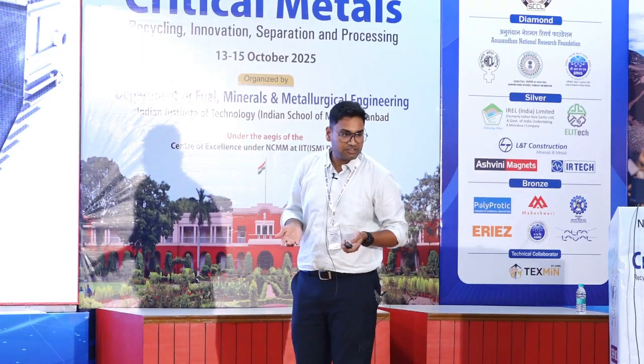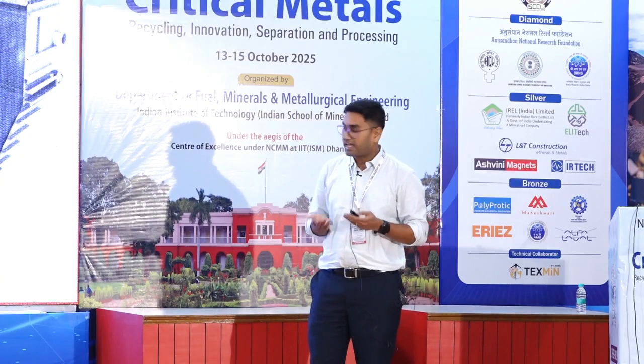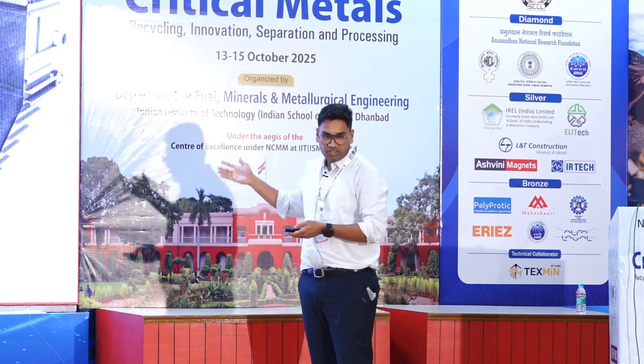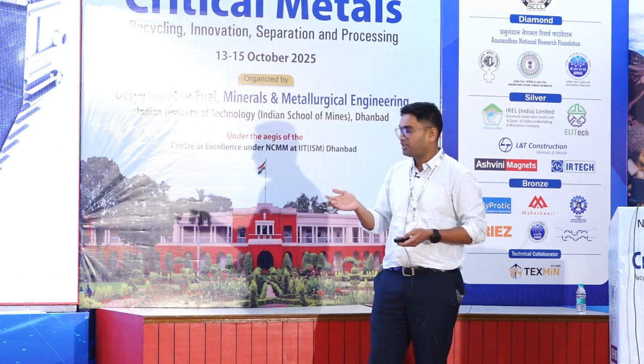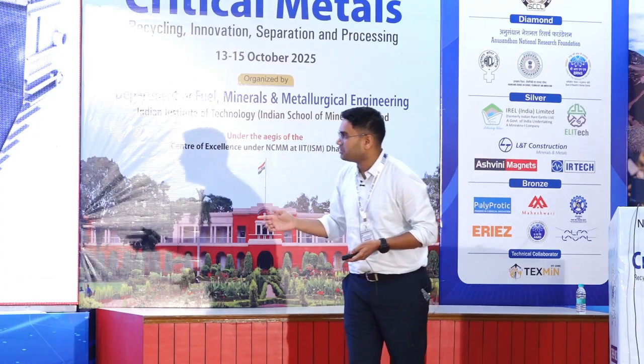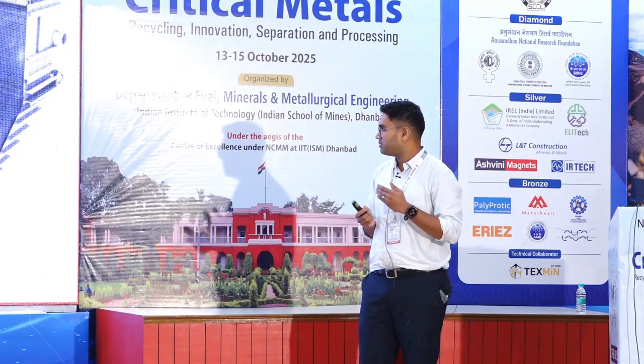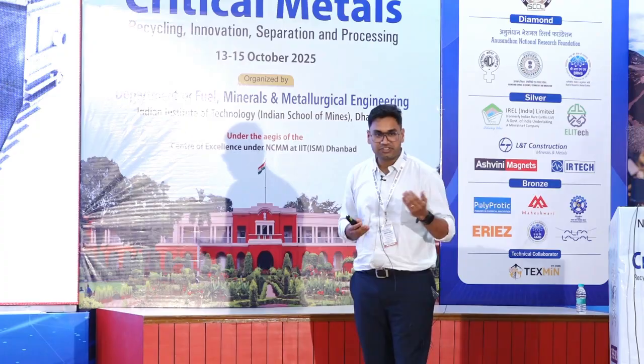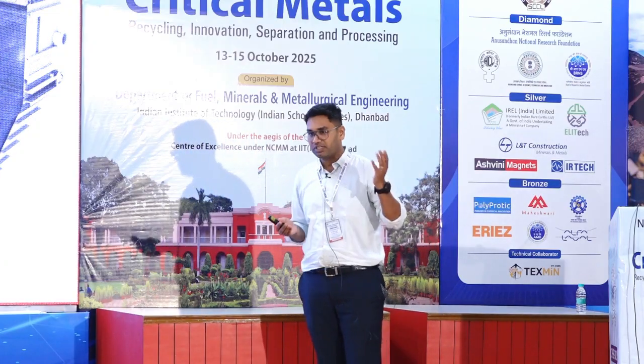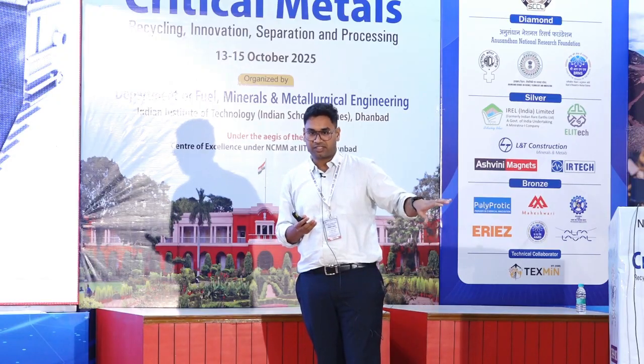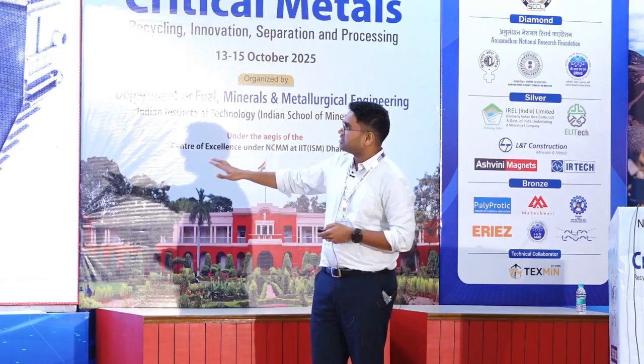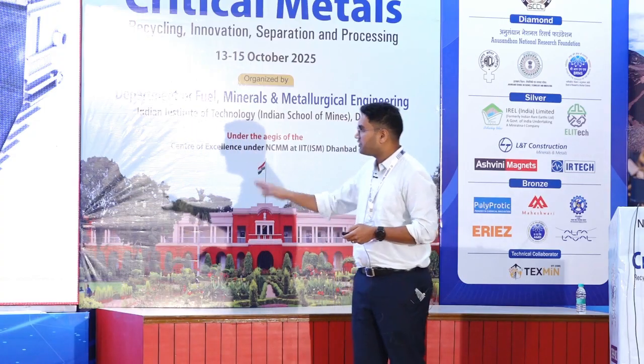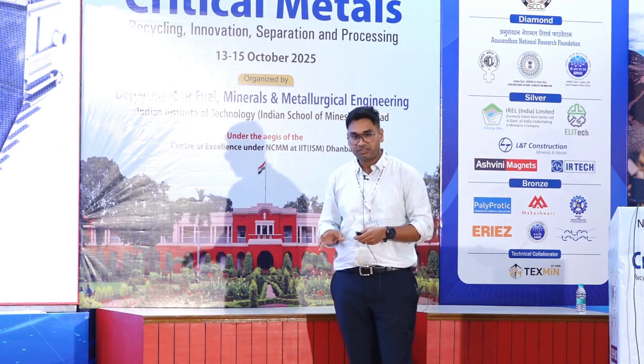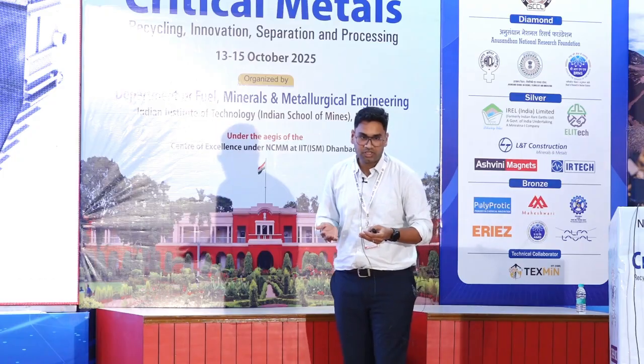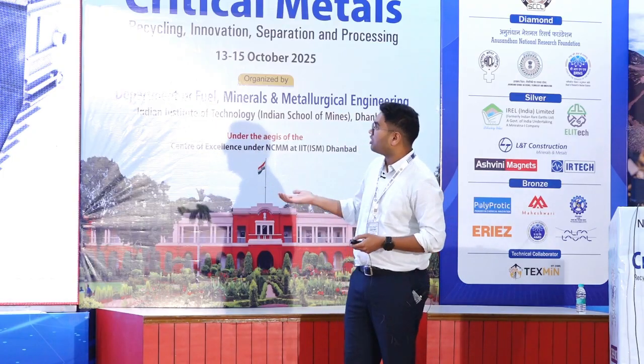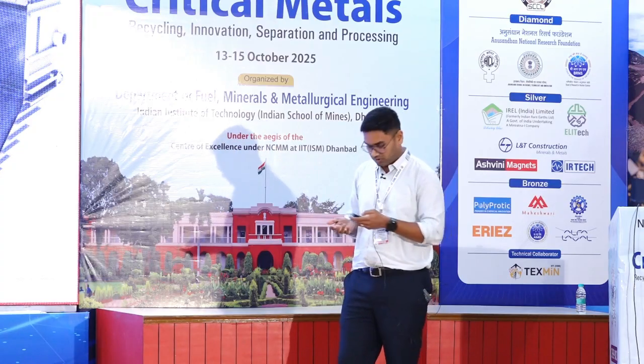The advantage of using a cross flow classifier is that it has very high capacity. It is very precise, majorly because it uses a very fundamental equation, Stokes' law, to do the classification, and it is not dependent on the fluctuation in the feed stream, and therefore it can work efficiently even if there are changes in the upstream or in the mine site. So this is something which we provide for density separation. We have tested these density separators for critical minerals other than the rare earths, for example copper, gold, nickel, cobalt, and everywhere these cross flow separators have been performing efficiently around the globe.